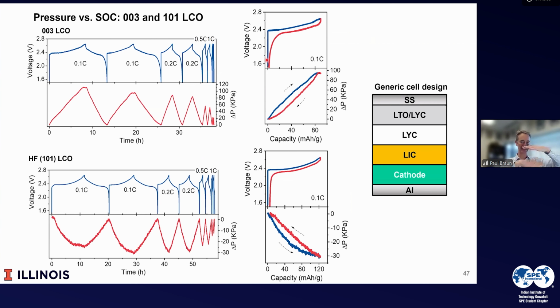And so what the advantage is that if you don't control the strain, here is pressure versus cycling. If I take a cell and I block it, what's happening is that the cathode is expanding and contracting, and that's leading to pressure changes. Well, when those pressures become negative or zero, that means material is moving apart and voids can form. And so if we want to minimize voiding, we want to minimize the point at which the system is being pulled apart as the cathode shrinks.